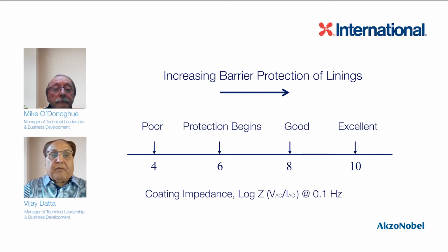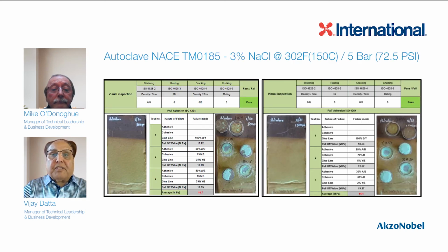Here is a typical example of an autoclave results. It's a run per NACE TM0185. In this case, we have a 3% sodium chloride solution at 300 degrees Fahrenheit and a little over 70 psi. Once the panels are exposed and evaluated, there were no blistering, cracking, or rusting on any of those 302F panels, and it gives excellent adhesion to the steel.